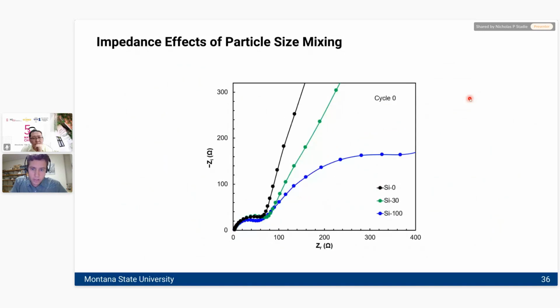Here we have cycle 0, and I'll show you a later cycle, to see what's going on in different mixture combinations. When you have a pure micron-sized particle versus a 30% mixture versus a 100% nano system in blue, you have pretty similar effects going on at the electrolyte-electrode interface, which is what this first semicircle represents, but very different behavior within the bulk of the electrode. The silicon micron-sized particle has a very resistive effect for lithiation in cycle 0 as compared to the nanophase. This might make logical sense: if you have a smaller particle, you also have maybe more defects, and lots of reasons why lithium might have less resistance moving into the nanophase material versus the micron.